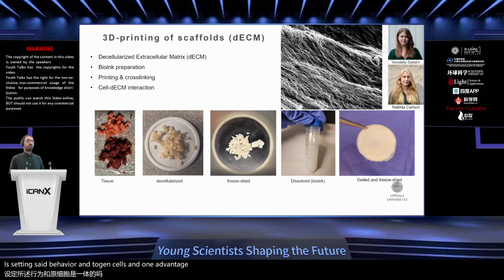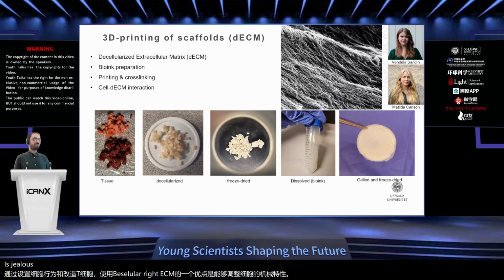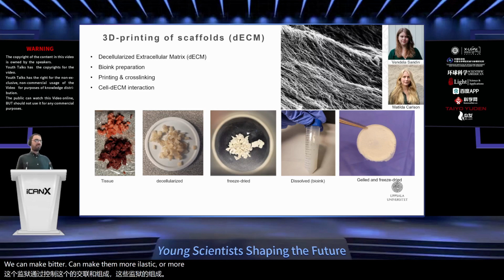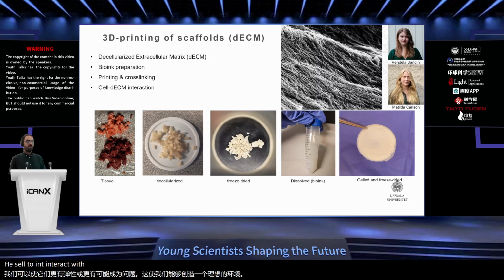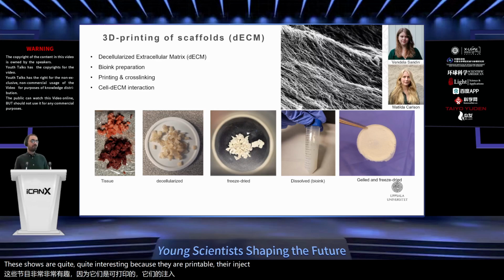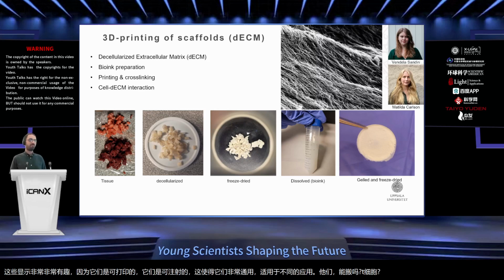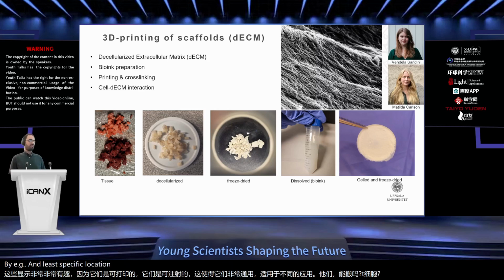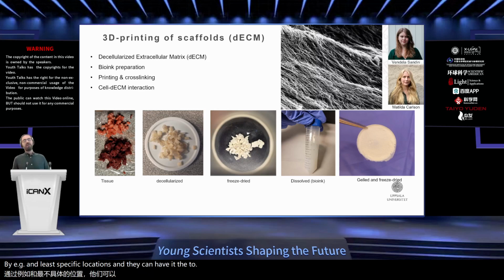And one advantage of using decellularized ECM is the ability to adjust the mechanical properties of these gels. By controlling the cross-linking and composition of these gels, we can make them more elastic or more like native tissues. This allows us to create an ideal environment for T cells to interact with. These gels are quite interesting because they are printable and injectable, and it makes them quite versatile for different applications. They can carry T cells into the body, for example, and release them at specific locations, and they can have a therapeutic impact for a longer term by containing the cells inside of them.